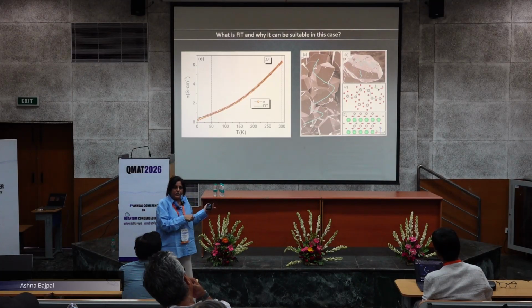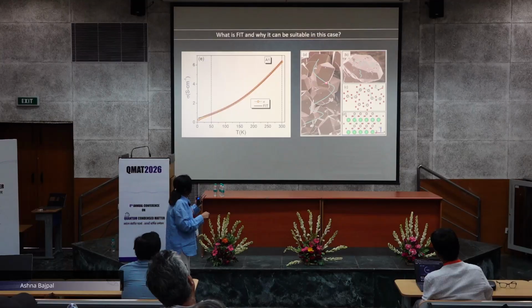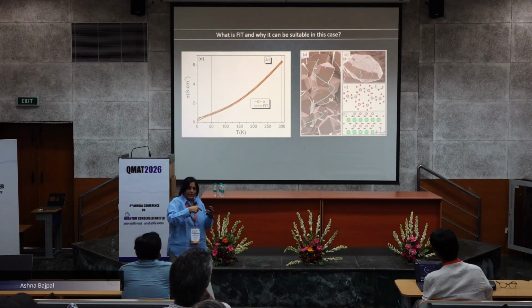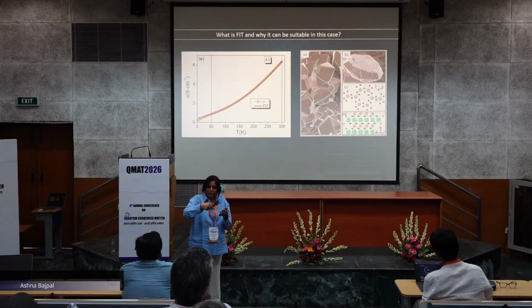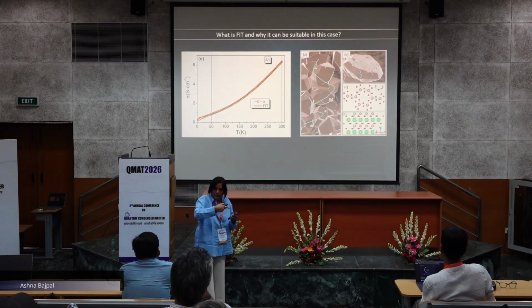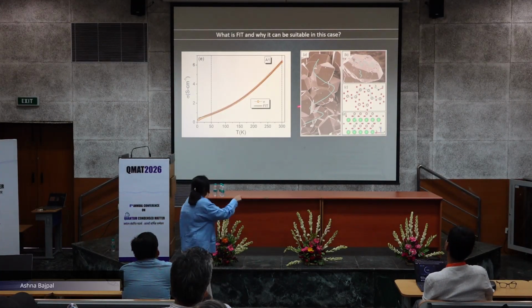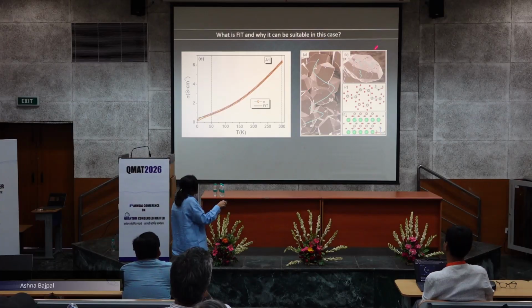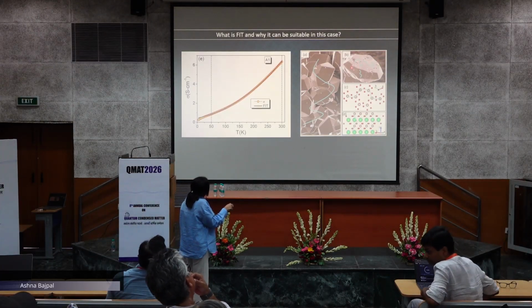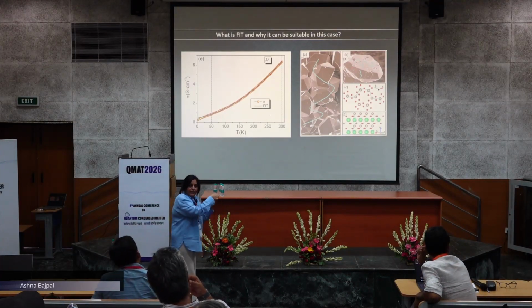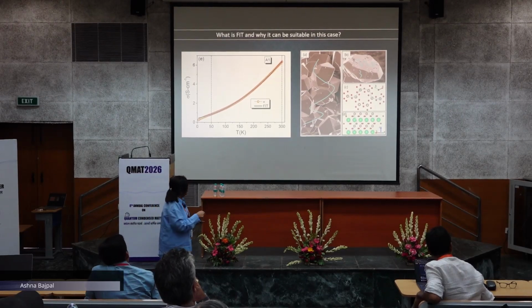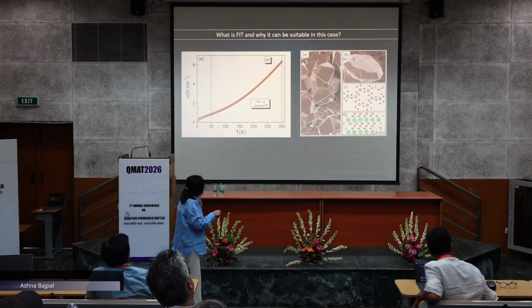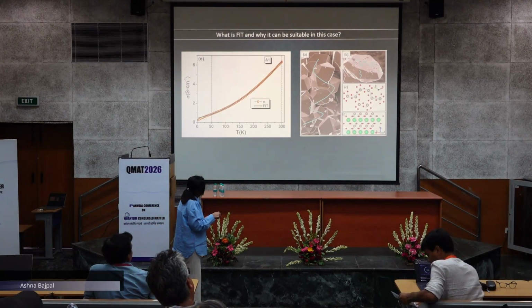In such a situation, like in a disordered semiconductor, basically you have two scenarios. You have a conducting grain, and then there is a barrier before it meets another grain, and there can be tunneling. So this is inter-grain tunneling, grain to grain tunneling. Another possible mechanism, the way it fitted so well in the entire temperature range. So if you look into the crystallographic structure, basically you have these Ru-O, Ru planes.